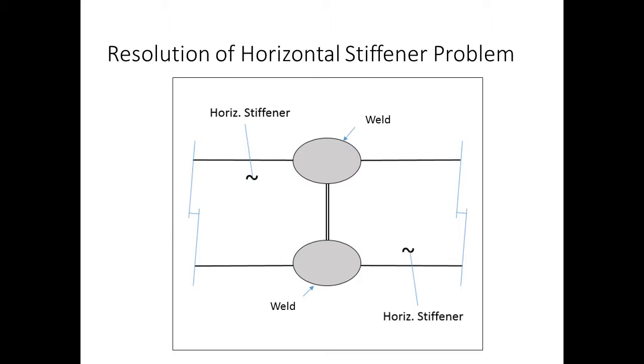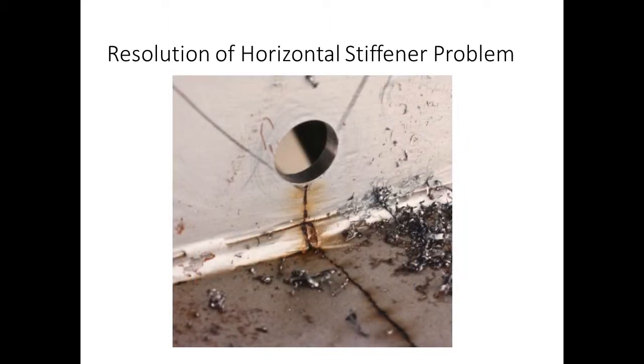So the inspectors went out in the field and started looking at these details, and here's one that they found. You can see that the horizontal stiffener has developed a fatigue crack that separated it. The crack jumped the attachment weld and is working its way into the web before it was stopped with the check hole.